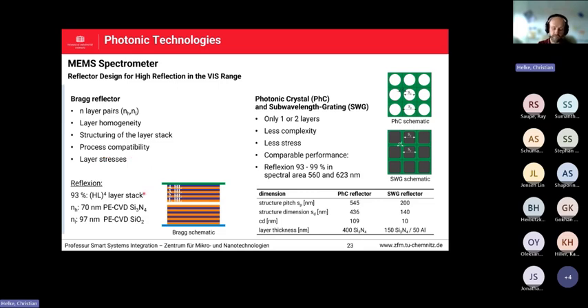So, for example, if we go to this example, which we will show now, we would need a 4-pair layer stack of silicon nitride and silicon dioxide layers, resulting here in 93% reflection. From a simulation point of view, it looks really nice and easy, but for the technology it's also quite complex because it's nanometer scale. But the images show that you need just one or two layers. The complexity from this engineering looks less. The stress is just from one material, the silicon nitride membrane itself with holes or with the metal stack on it. The performance from a simulation point of view looks nearly the same, with 93 to 99% in the spectral range of 560 to 620 nanometers like this one.